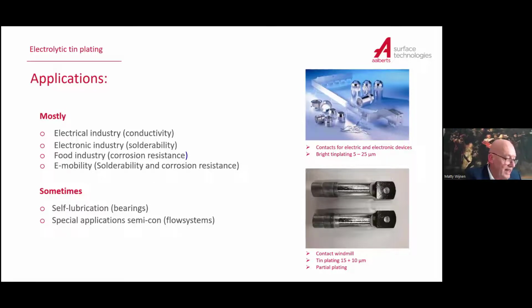Then we look at the next one, that's the tin plating. Now, tin plating is mostly used in the electrical industry for conductivity, in the electronic industry for solderability, in the food industry for corrosion resistance, and in e-mobility, solderability and corrosion resistance. E-mobility is also an upcoming market in which you see it more and more. The advantage of tin is when you solder, you melt the metal itself. That means soldering tin, you melt your metal and make contact with the melt, it gets solidified again, and that makes your connection. That's the way in which you can solder tin very well.